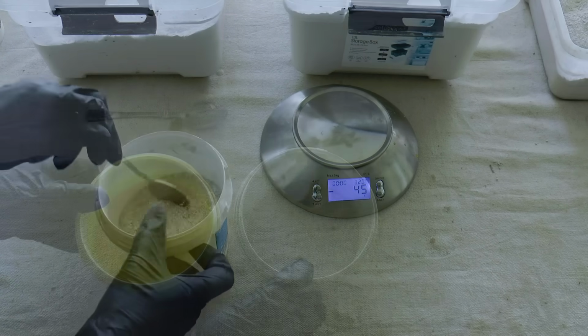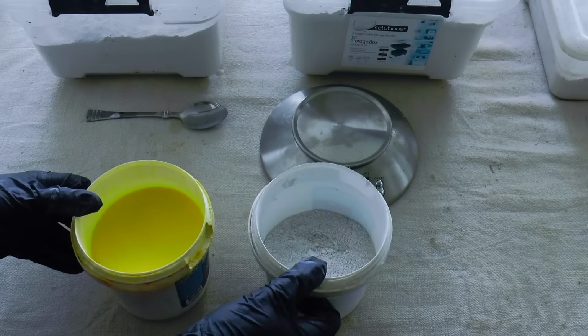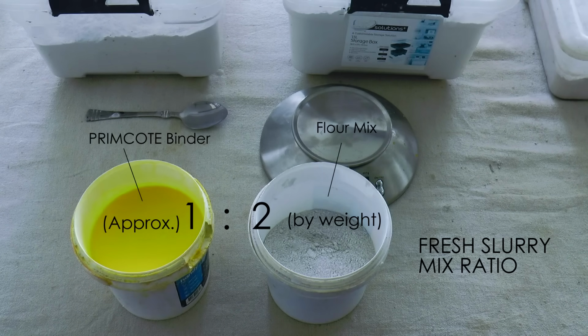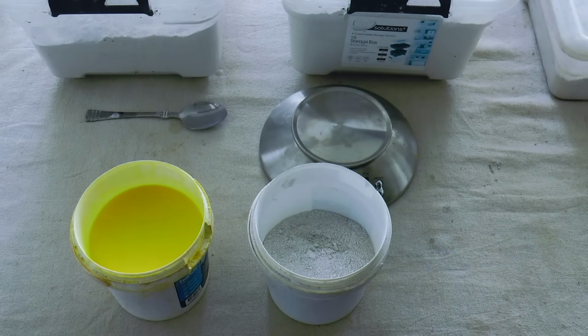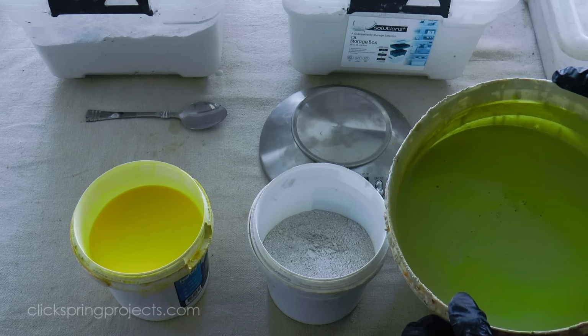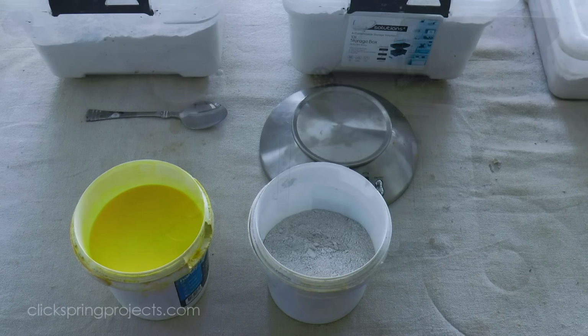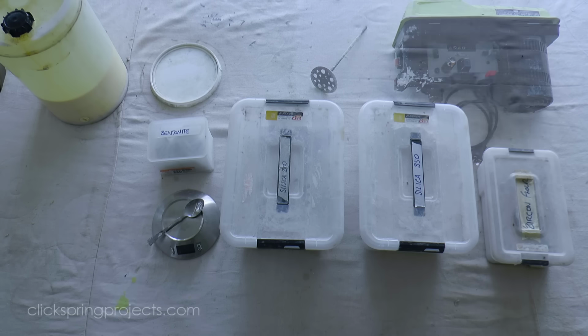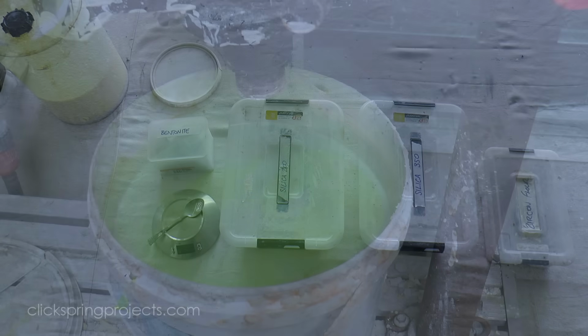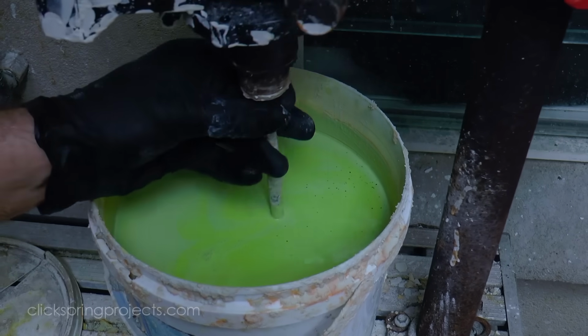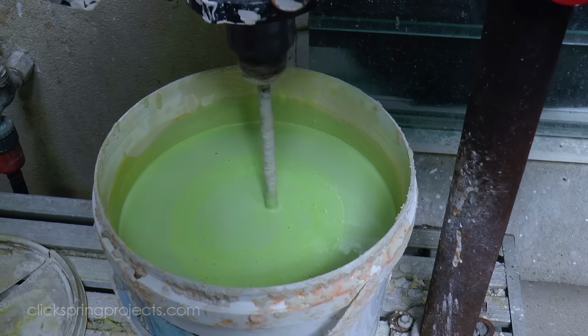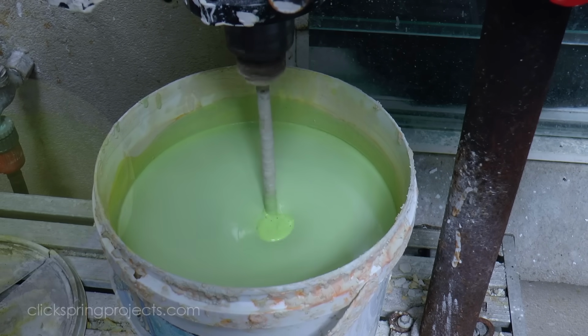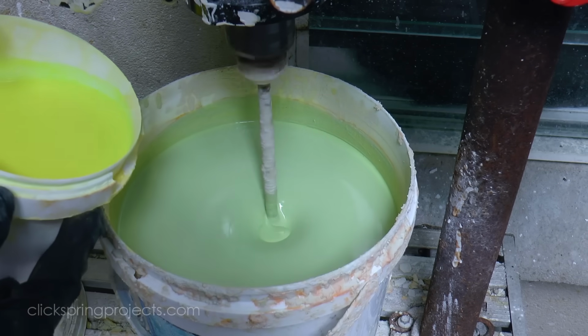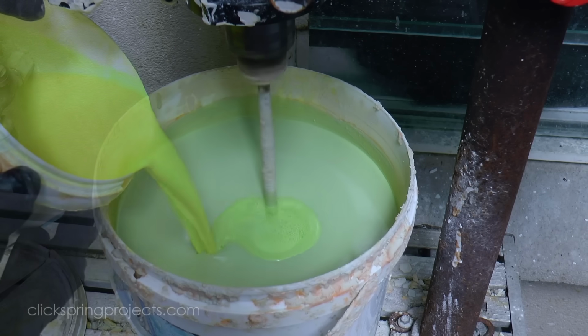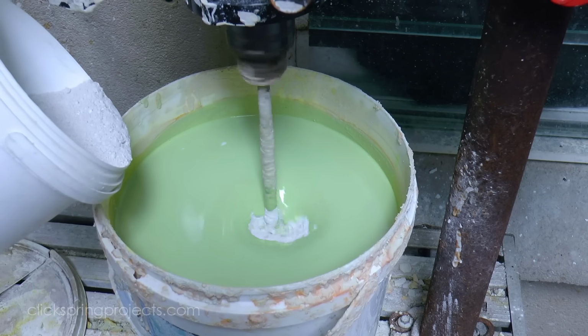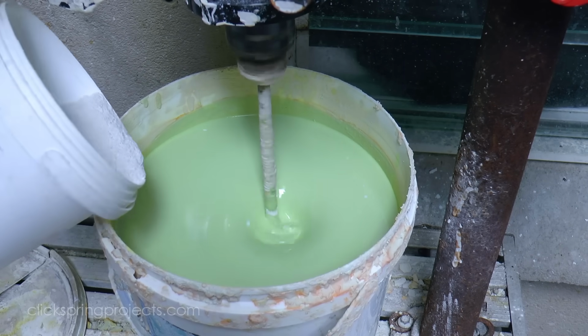If producing a fresh mix, the colloidal silica and the flour are mixed together in roughly the proportion on screen. But in this case, I'm topping up an existing slurry mix. In each case, the process of combining the binder and flour is much the same. With a suitable mixing device activated to suspend the mix, first the binder is added as required, and then the flour is gradually added, making sure that each addition has become wetted before adding more. This continues until the desired viscosity is achieved.